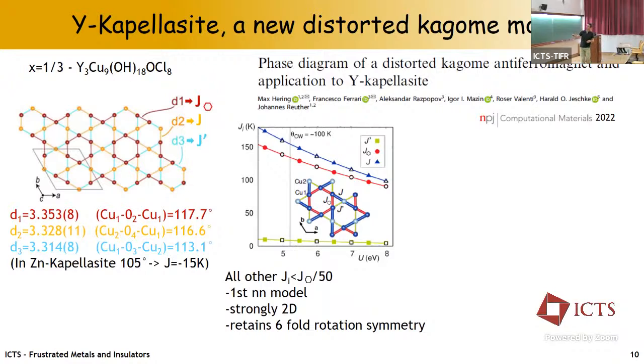And so the main interactions are related to the three distances that you have there. Two are more or less equal. I should mention that J and J prime are symmetrical, actually, so you can exchange them as you wish. So two of them, the one on the perfect hexagon and one of the links, are of the same order of magnitude, 150 Kelvin, and the other one is found to be very small. So we end up with this kind of perfect hexagon linked by one double bond like that, just in one direction. Okay.